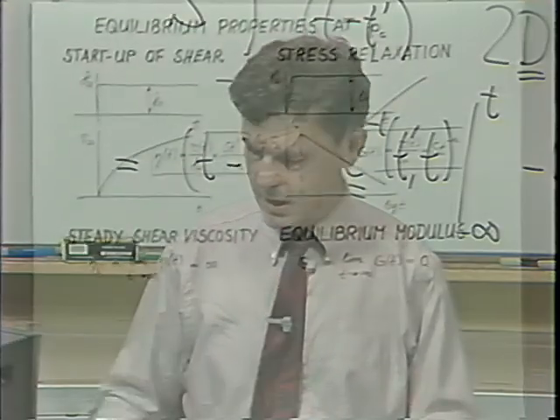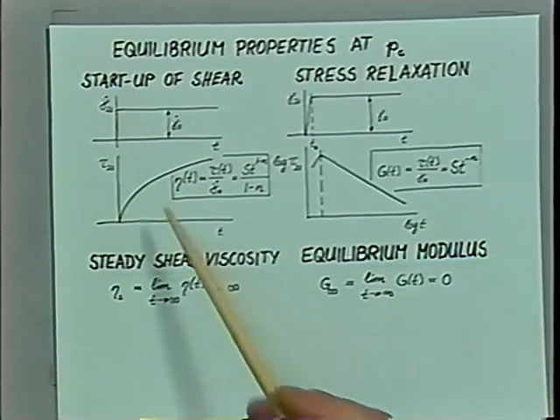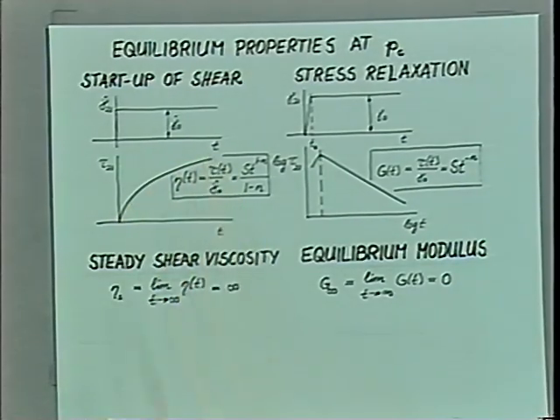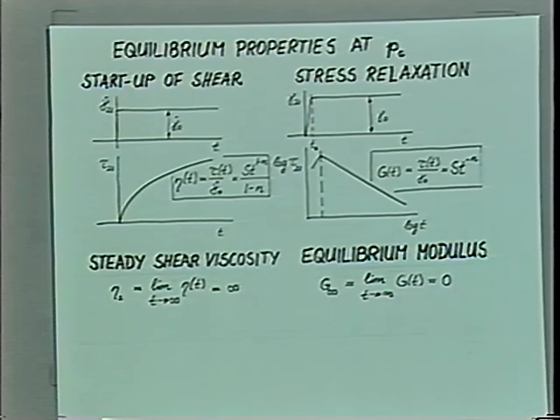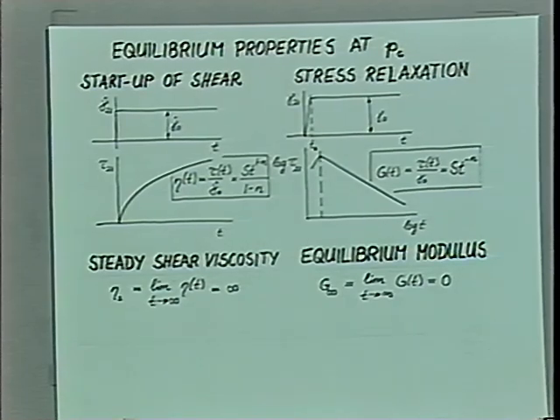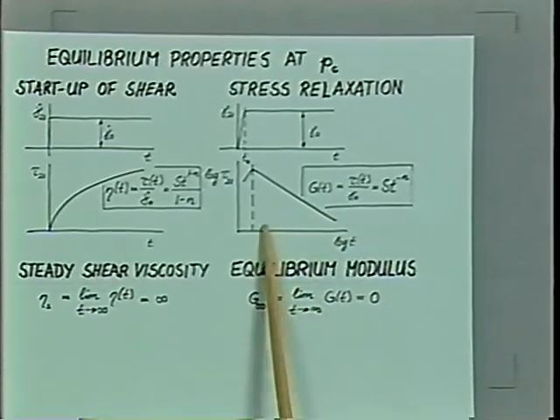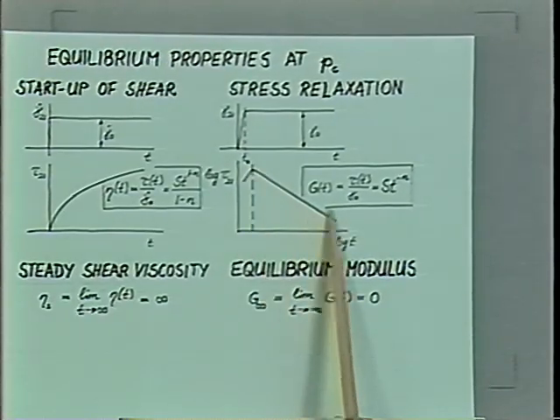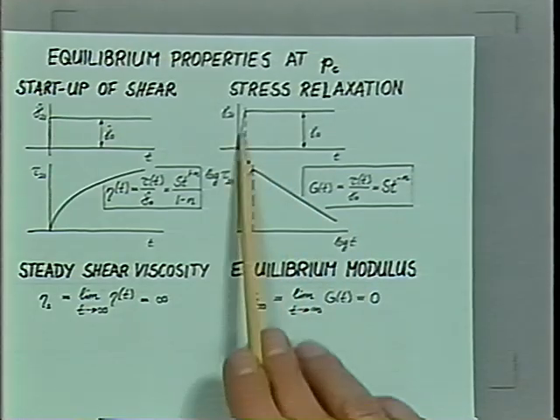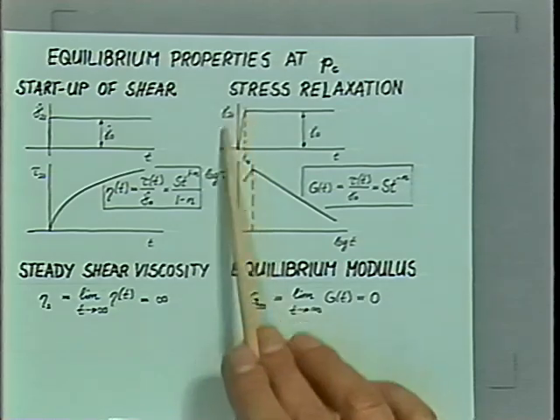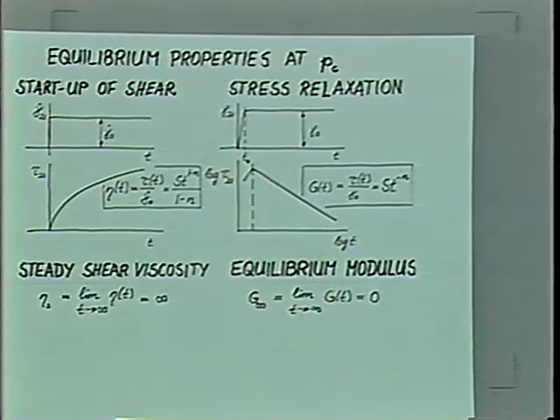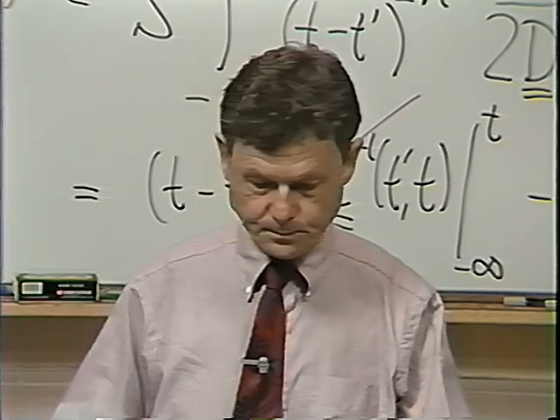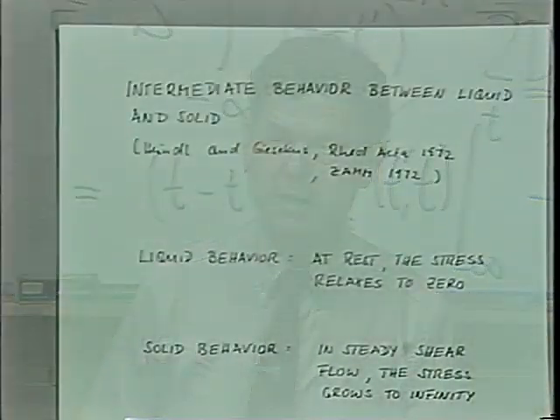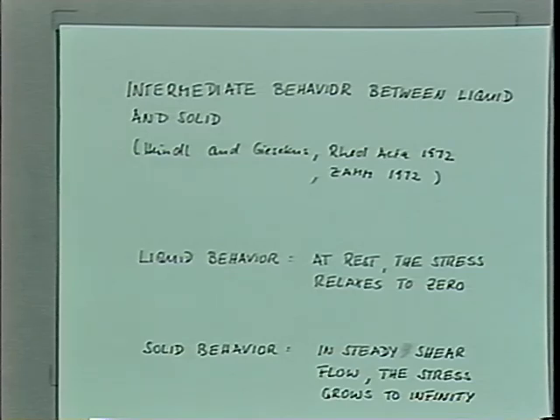To conclude this here with 2 more figures here. This is the viscosity, which is going to infinity in the material. When you start up shear flow, the viscosity grows and grows. The stress grows to a diverging value, which is the property of a solid, really. And the relaxation is described by a modulus which decays, and in this fashion. In the modeling, I neglected the startup, finite starting time, but it doesn't really matter at long times. It decays in this fashion. So this is the relaxation in a power law in time. So the material at the gel point has this intermediate quality between liquid and solids.